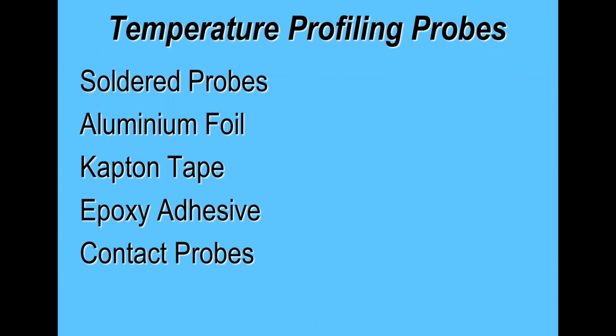First of all, the best is solder them in place. That tends to give the best performance. And pretty much equal to that is aluminium foil. You want to make sure the junction temperature is measuring the temperature you want. Kapton tape really is useful to hold the thermocouple wire to the board, but not to hold the junction to the board. What tends to happen is it lifts, and the thermocouple bead measures air temperature rather than board temperature.